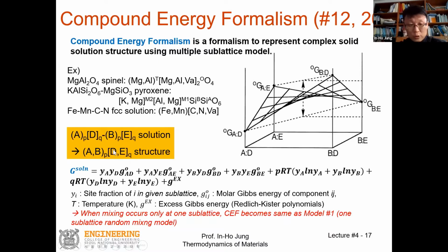And we have also the BD or DE interaction parameter, LDE, assuming the first sublattice has A species only, and DE with the first sublattice having only B. And then we have A, B, C, D all together as an excess parameter as well. So there's a little bit more complex actual formula for the L parameter, but it's almost the same as the one sublattice model. The formula itself is the one sublattice model.